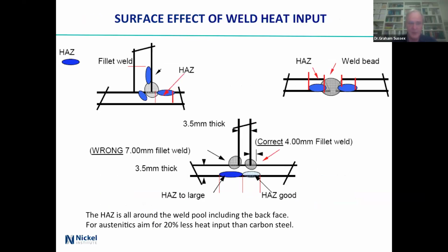Here's what happens if you put too much heat in. You should have a weld bead down the bottom, probably the easiest one here, where we're talking about 4 millimeter should be right, and so the heat tint on the back is okay. You go a lot faster, a lot thicker, 7 millimeter fillet instead of 3.5, and you get an enormous area. And so you've got to worry about the backside, but also you've got to worry about how far the heat tint spreads up.